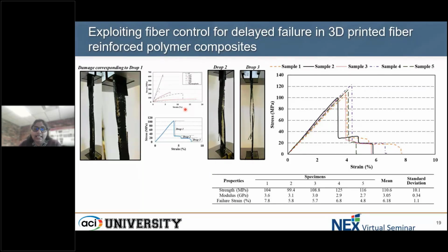Then we saw a really abrupt failure, which is indicated as drop 1 here. If you see, all the 5 composites we tested demonstrate similar kind of behavior. After the drop 1, the higher angle layers, such as the 45 degrees, observed some debonding from the remaining composite. So this is corresponding to drop 1. Then we have drop 2 here, which was followed by a small drop. Though abrupt, it was smaller in capacity. And then we had drop 3, which the result was basically the entire damage resulting to failure of the coupon itself.